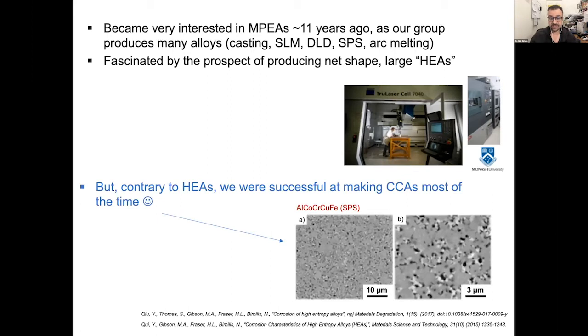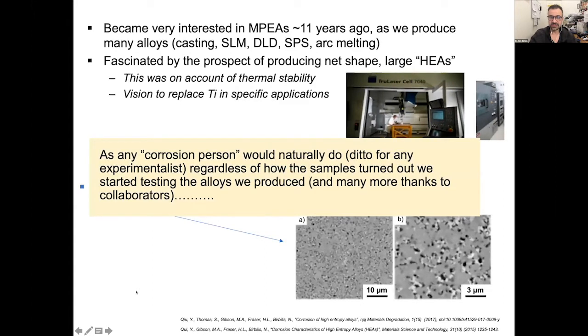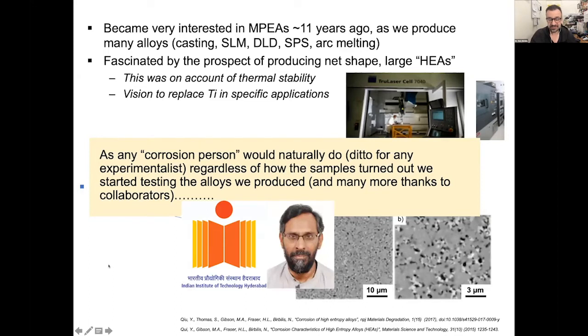They ended up, and we ended up making multi-phase alloys, contrary to trying to make single-phase alloys, even when using equiatomic proportions. And so like any good corrosion group or even bad corrosion group, when you make samples, you want to start doing corrosion testing at some point, or someone wants to do corrosion testing. And fortunately, we found some other early collaborators at the time, including B.S. Murthy, who was at the time at IIT Madras and is now I think running the whole university at the Indian Institute of Technology at Hyderabad.